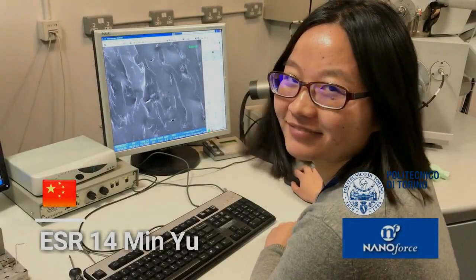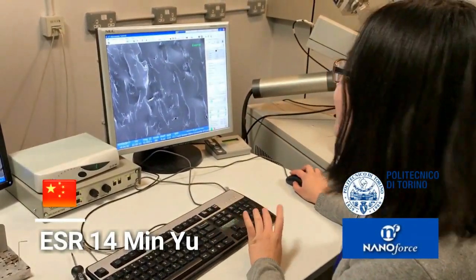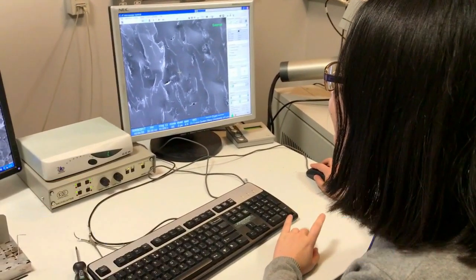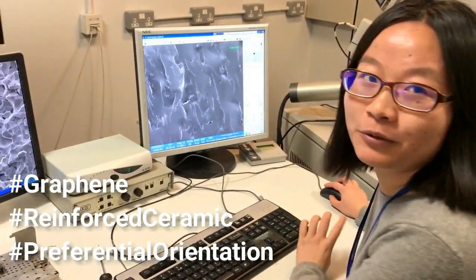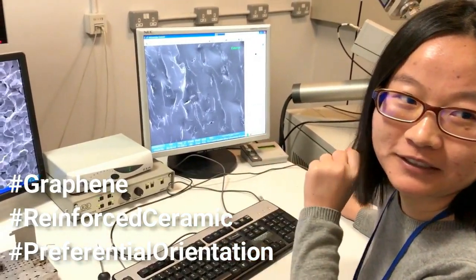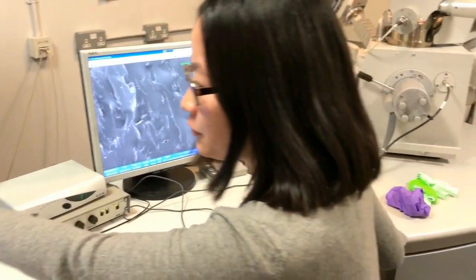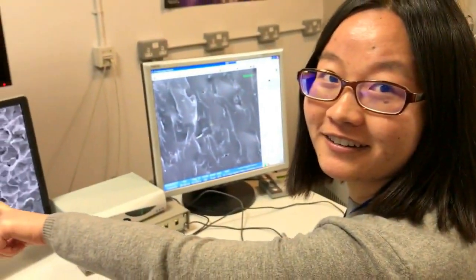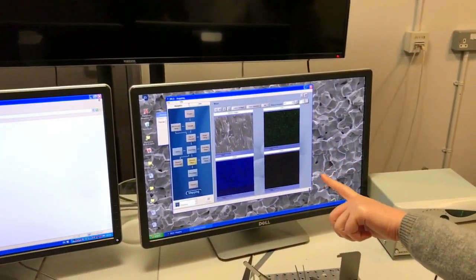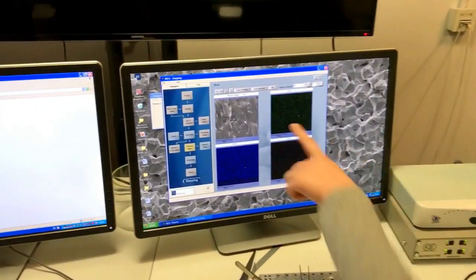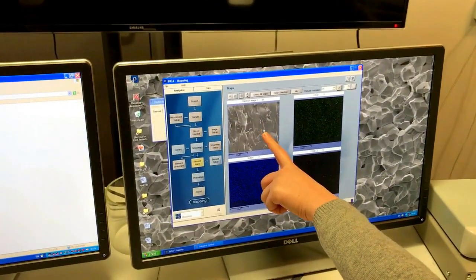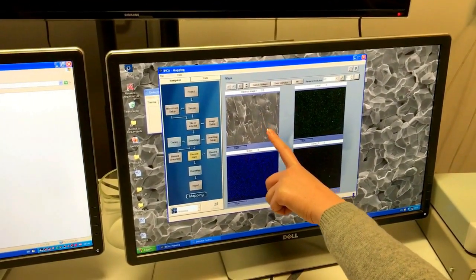After we obtain a pellet, we can observe the microstructure and measure the thermoelectric properties in order to establish the efficiency of the material. Hi, this is my material. It's a silicon oxycarbide with graphene oxide composite. And here you can see we are doing the mapping, and here this is a graphene oxide layer in the